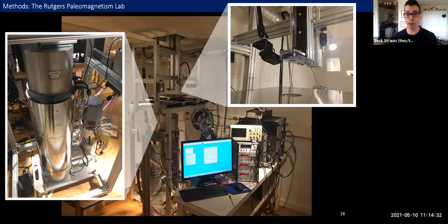You can also see our sample handling system. You might be able to make out this clear quartz glass tube, which we could apply vacuum at the end in order to pick up and carry our samples up and down through that instrument stack so that we could pre-program some fairly complex experiments without having to sit there and press a button every 30 seconds.